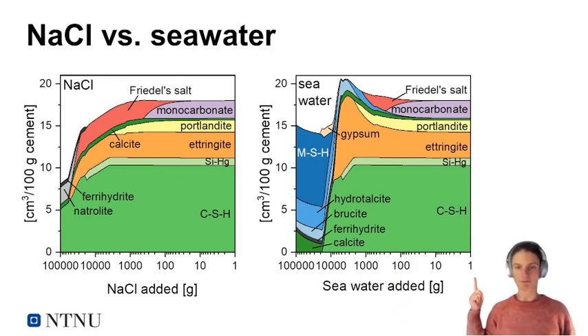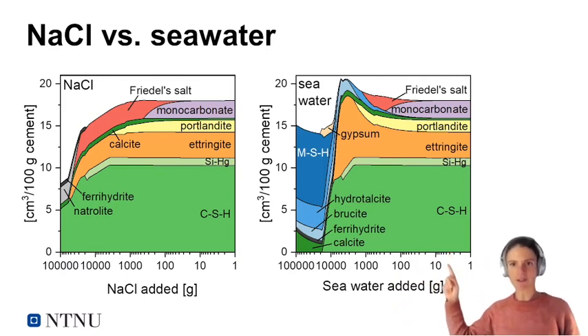So at 1, there is very little seawater it is exposed to, so we have the normal hydrate assemblage, C-S-H, and so on. When we're adding more and more seawater, we again see that the purple phase, monocarbonate, is transforming to Friedel's salt, the red phase. And in addition, we can see this orange phase, ettringite, is increasing in volume. And that is due to the sulfur in the seawater. We're getting more and more ettringite. And that leads to a total increase of the volume of our hydration phases. So this could indicate a tightening of the pore structure, potentially.